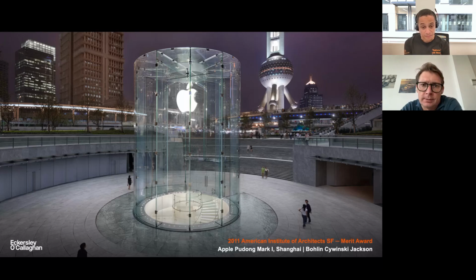And when we started out looking at this project, we had all sorts of ideas about cross-laminating curved glass. But the difficulty with curved glass is that it's very difficult to get the same level of tolerance as for flat glass. And so we ended up with something that was either fitting heavy or might have quite large gaps or variations in the interlayer. And so speaking with the manufacturer, they said, well, we've got this idea for a furnace which is a continuous curving furnace. So this was made possible through advancement in technology.